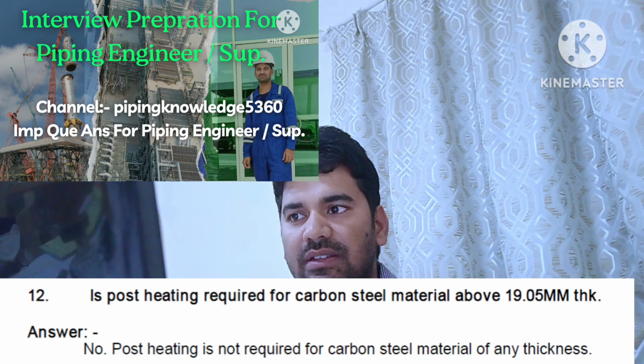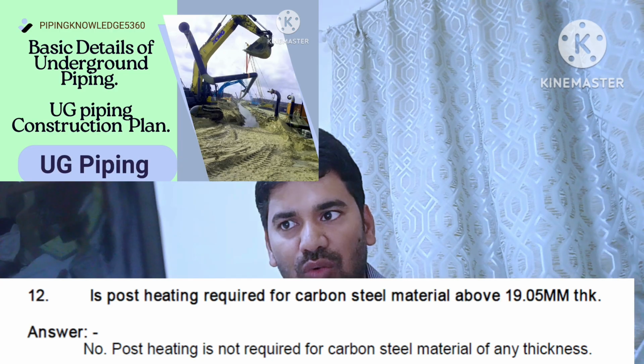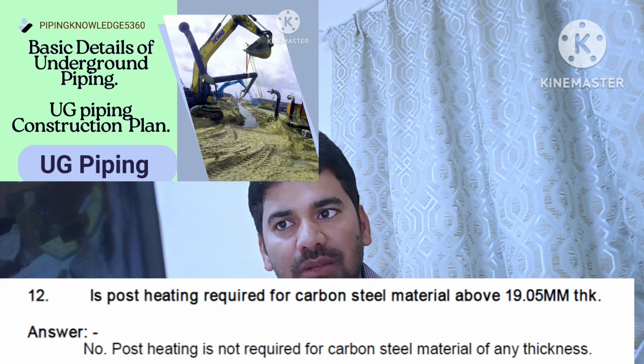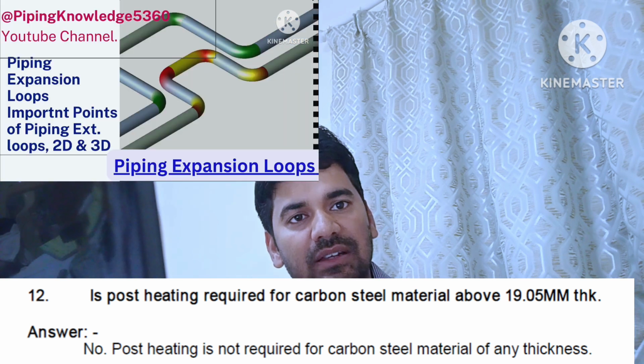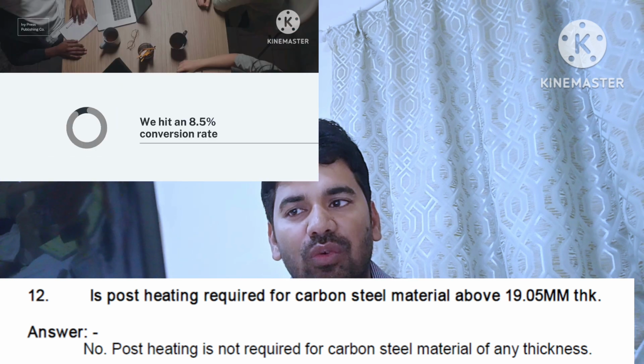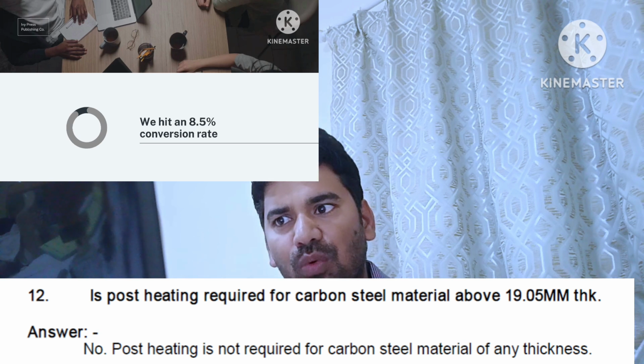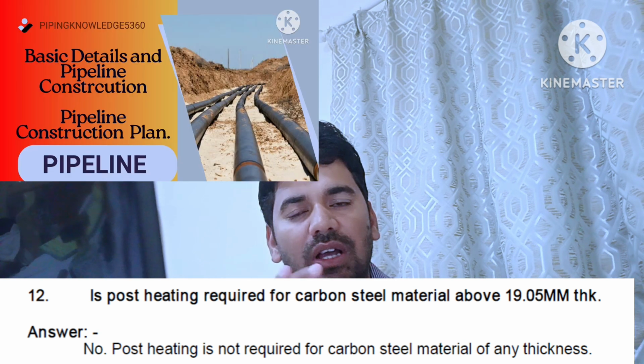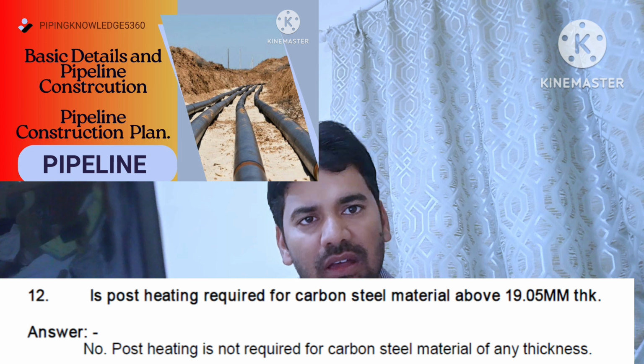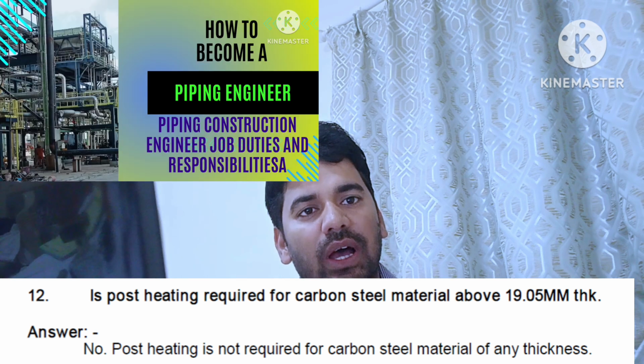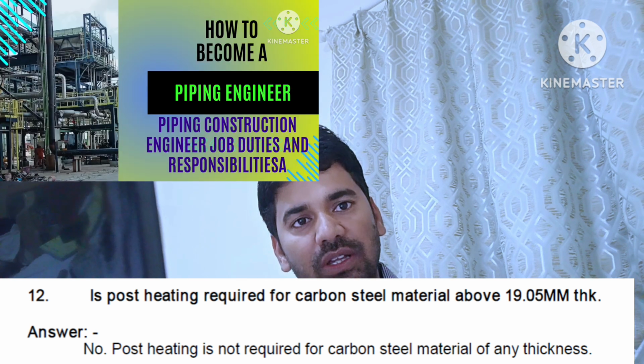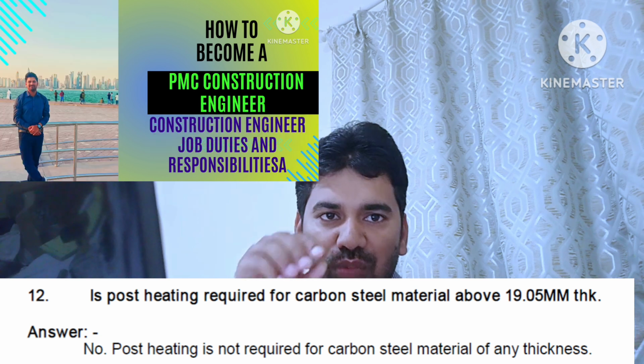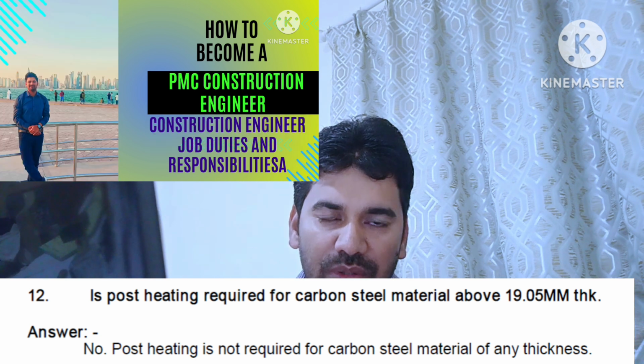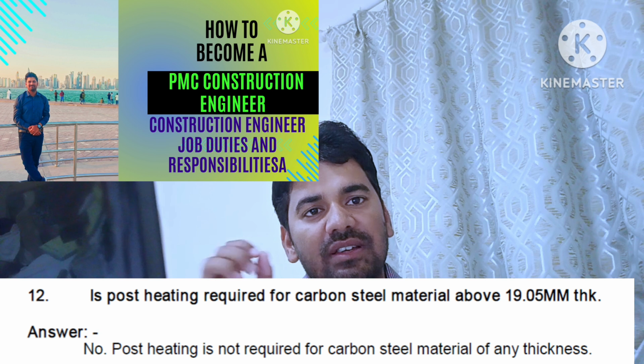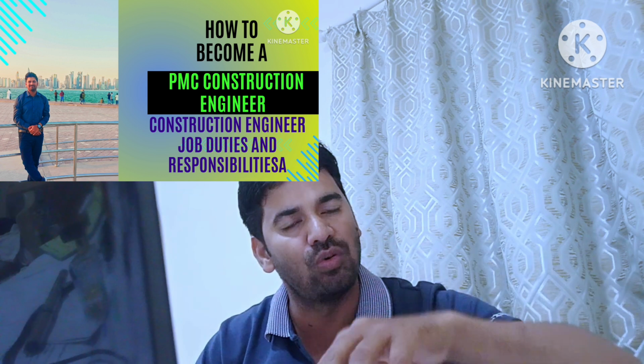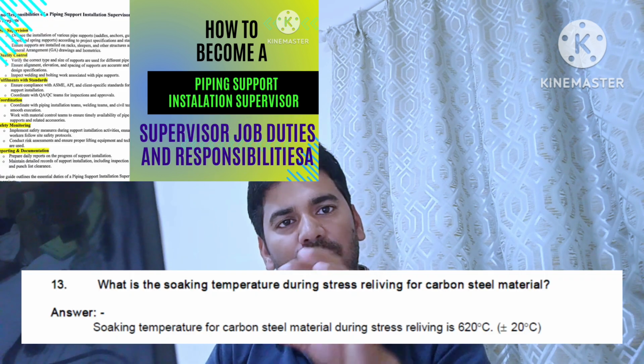Okay, the next question is whether post heating is required. Post heating is not required for carbon steel pipe of any thickness. If your CS pipe thickness is 19.05 mm or more, then you require preheating, and the preheating temperature is 80 degrees Celsius. But there is no post heating in carbon steel pipe.